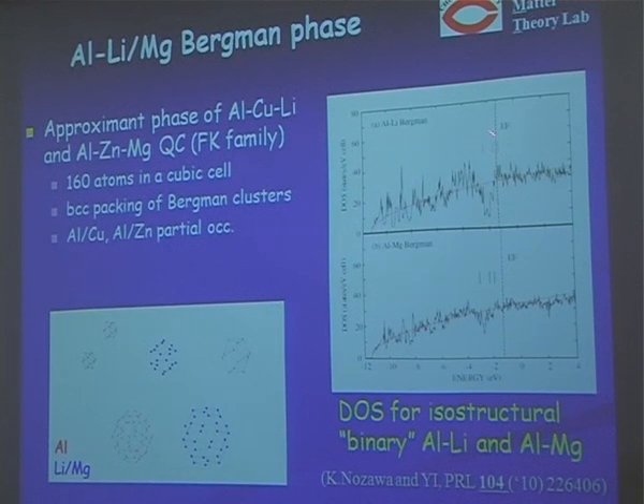And actually the free electron energy calculated from the zone boundary wave vector is located here. So again, the free electron energy at the zone boundary is very close to the pseudo gap. So it seems reasonable to assume that the strong scattering causes such a pseudo gap.